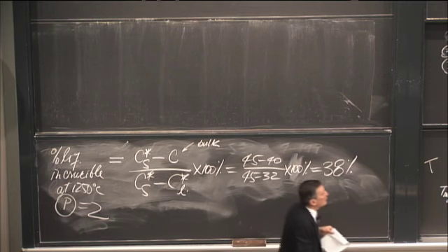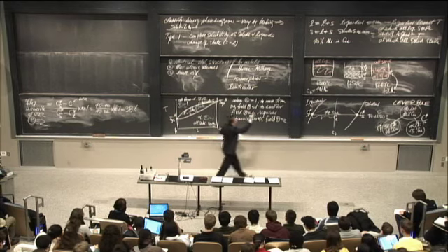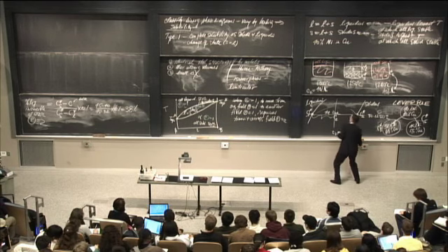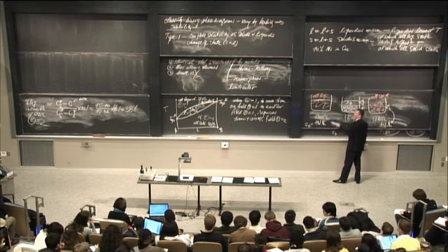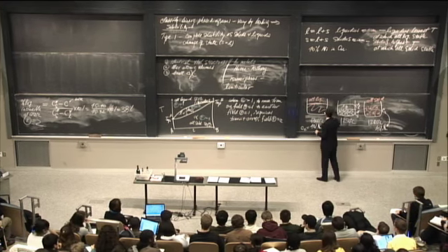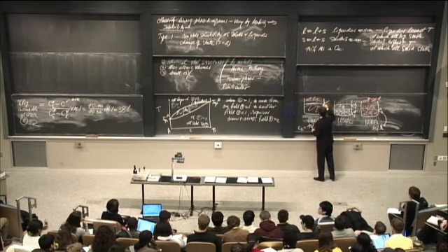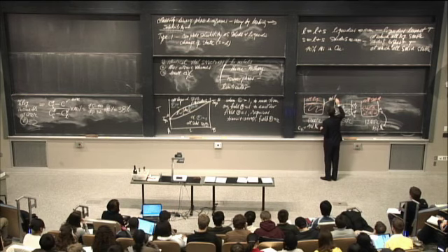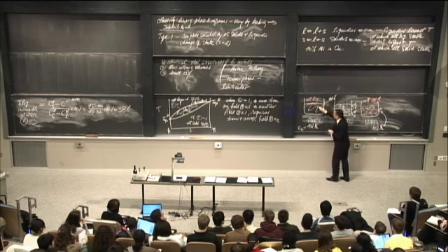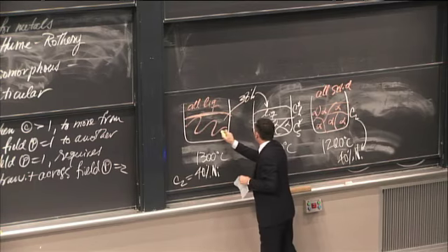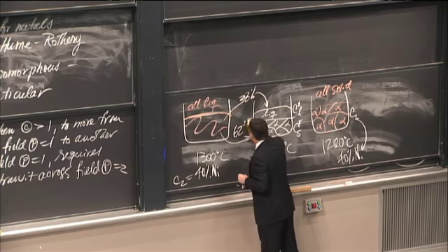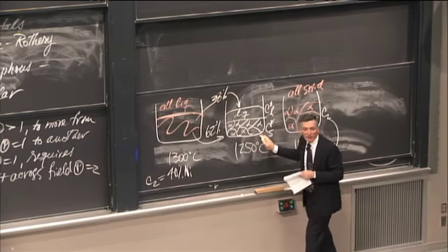So what that means is that if you take this amount of liquid here, based on conservation of mass, if you drop and hold at 1250, 38% of that volume is now sitting here in the liquid, which means 62% of it by volume has turned into solid.